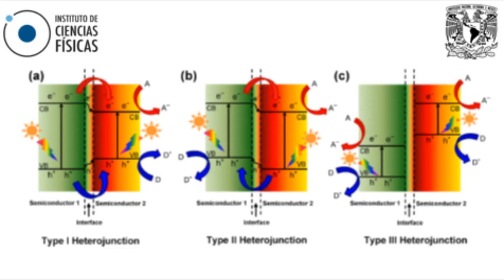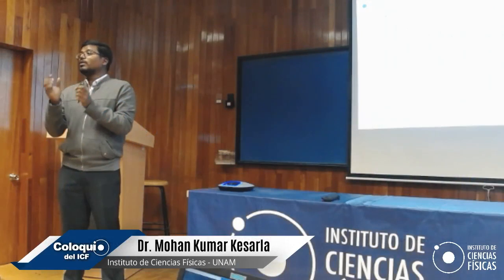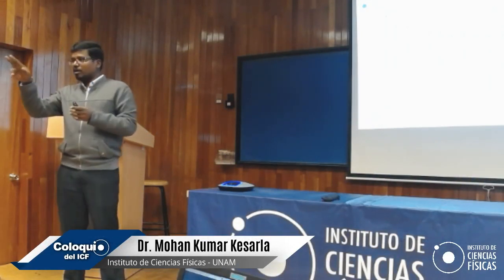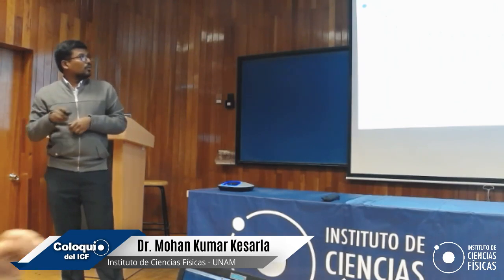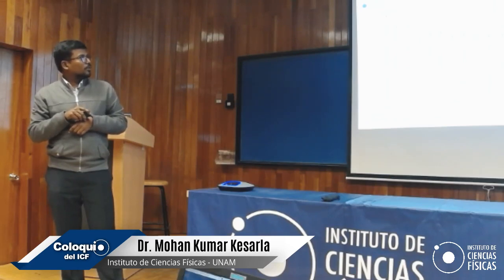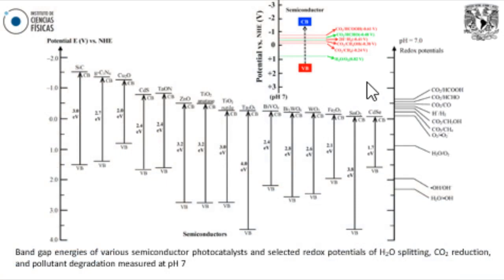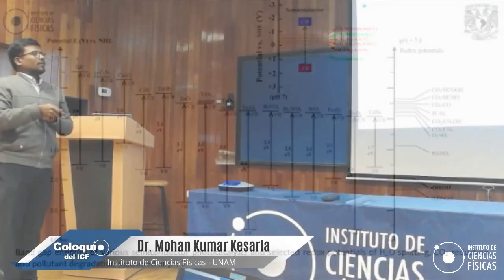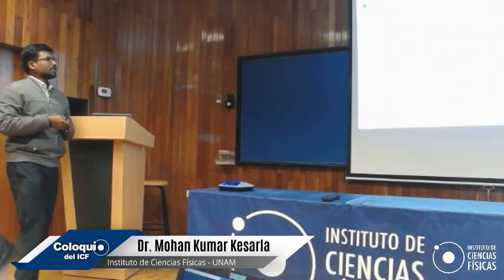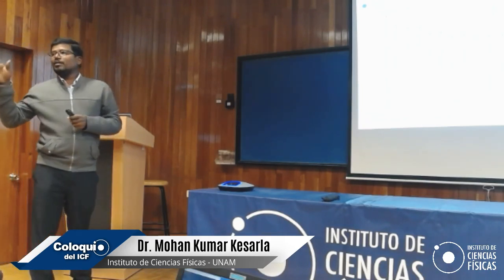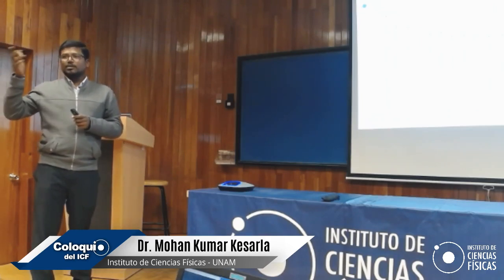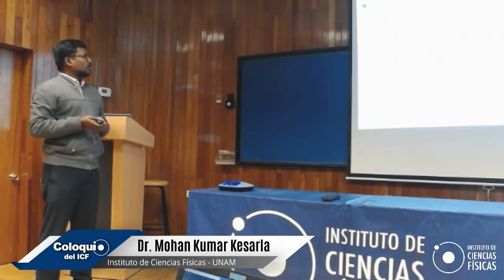Before forming a heterojunction, we should have a good grip on what type of heterojunction we are going to make. In order to generate hydrogen or to convert carbon dioxide into the respective solar fuels, we need these potentials. If the conduction band and valence band potentials lie below the required values, we can't use that particular semiconducting heterojunction for hydrogen production. That's why there's a huge chart here, potential versus normal hydrogen electrode, with the redox potentials of particular reactions like reduction and oxidation, conversion of carbon dioxide, production of hydrogen, or some oxidation reactions at pH 7. And what to keep in mind is that the reduction potential changes drastically with pH, so the pH of the solution is pretty important when we are working on hydrogen production.